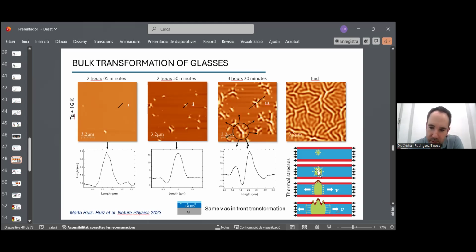And once it grows in this direction, it cannot grow larger because this is the thickness of the film, but eventually it will grow laterally, okay? And when it grows laterally, we have these kind of patterns which are produced due to the release of stress of this capping layer, okay? This is a mechanical effect, basically, and it goes laterally until the whole sample is transformed. Okay? So again, this is quite direct evidence that the system is transforming via bulk, but via bulk heterogeneously. Let's say some regions become liquid before other regions. Okay.